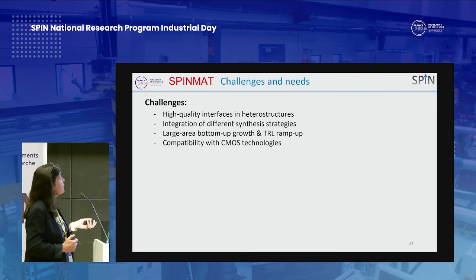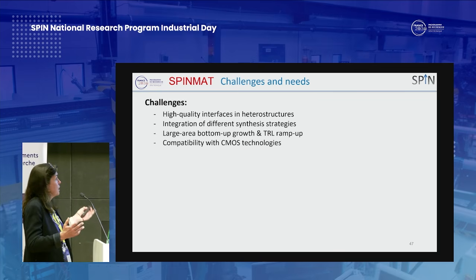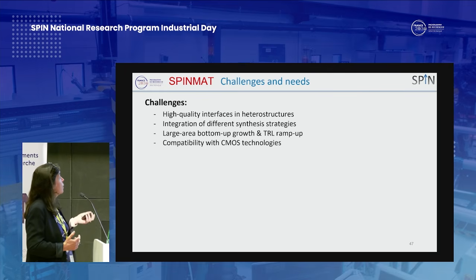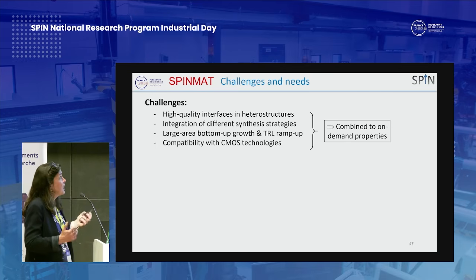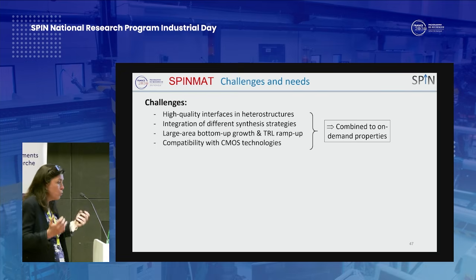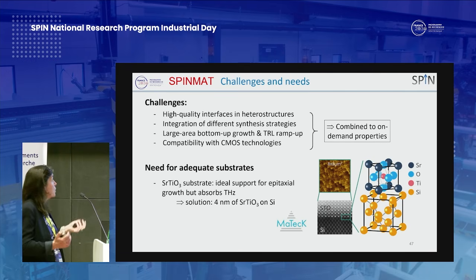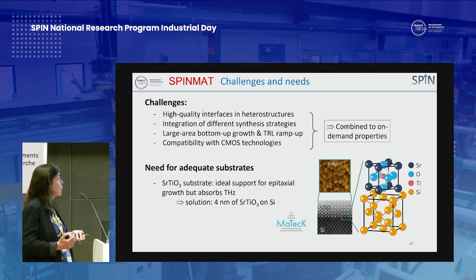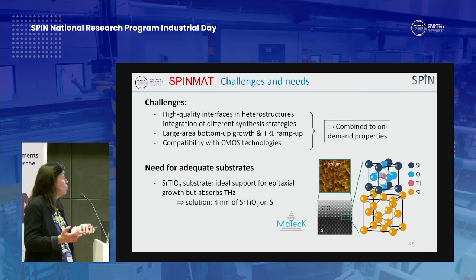And so high-quality interfaces, heterostructures, integration of different synthesis strategies, and that is particularly true when there is the growth of different types of material, large area bottom-up growth, TRL, compatibility with CMOS technology, and that is combined with on-demand property. So to answer this demand, we first need adequate substrates, and to illustrate that, for example, STO is the ideal substrate to grow most of the oxides, but it poses limits for terahertz characterization due to high absorption.